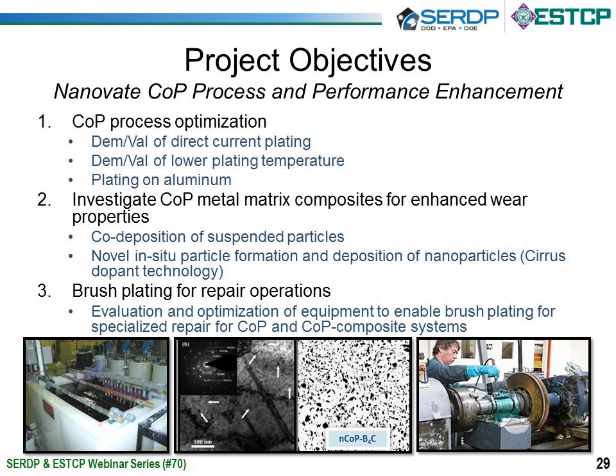The second main objective involves using the cobalt phosphorus metal coating and incorporating various hard phase particulates for enhancing the wear properties. We're doing this with a dual approach. One is the conventional method of adding suspended particles to the solution and co-depositing them. The other is working with Cirrus on novel in situ particle formation and deposition of very, very small nanoparticles using the Cirrus dopant technology. And the final objective is looking at how this technology can be applied specifically in brush plating and selective repair operations.